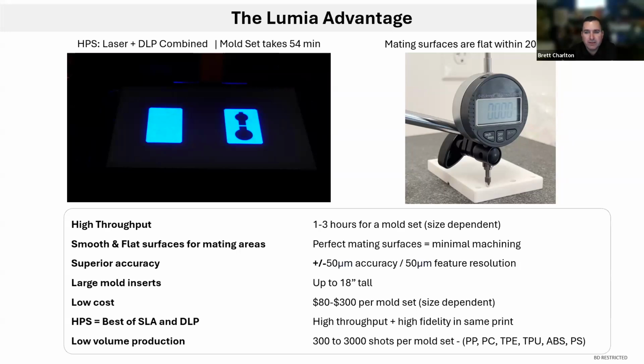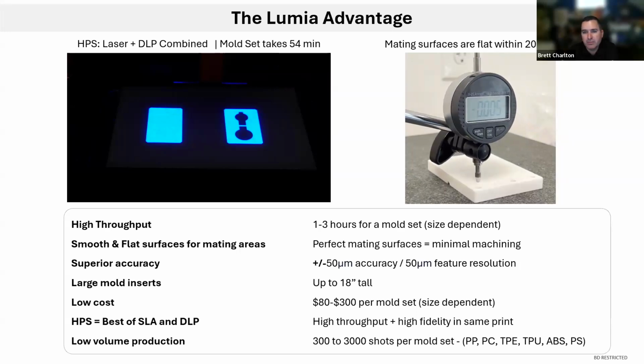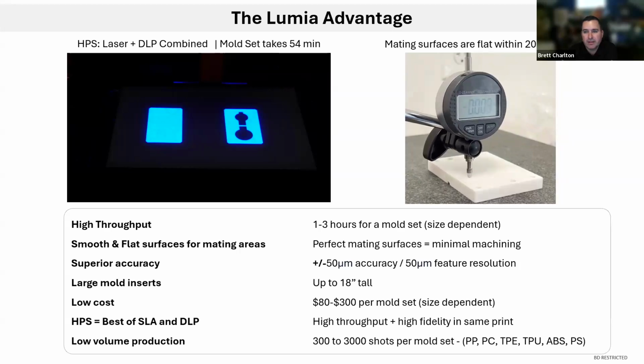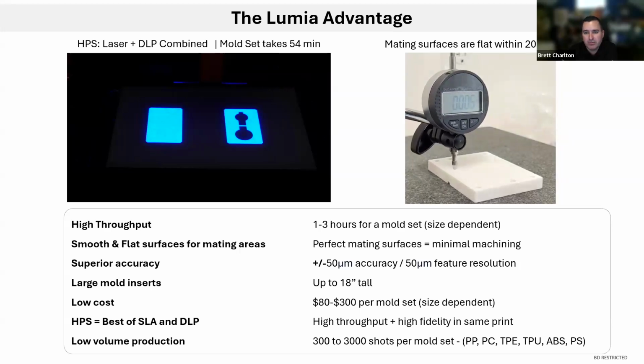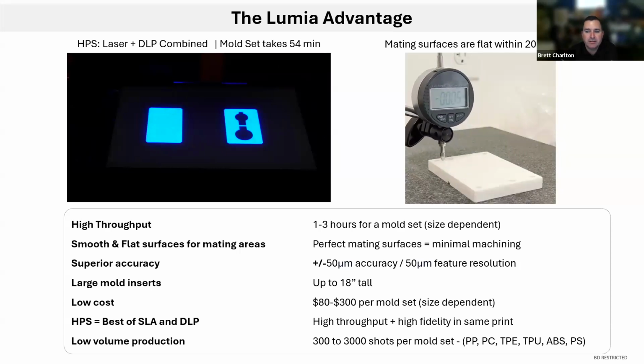Let's take a look at what we mean by flatness. You can see here that the surface maintains its flatness from front to back. The claim is within plus or minus 20 microns, but you can see here that the dial indicator is showing less than 10 microns or 0.010 millimeters from front to back on this parting line.